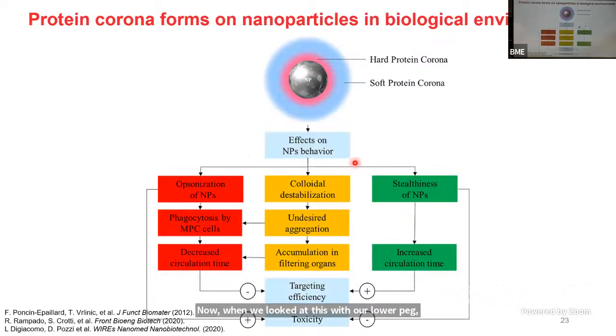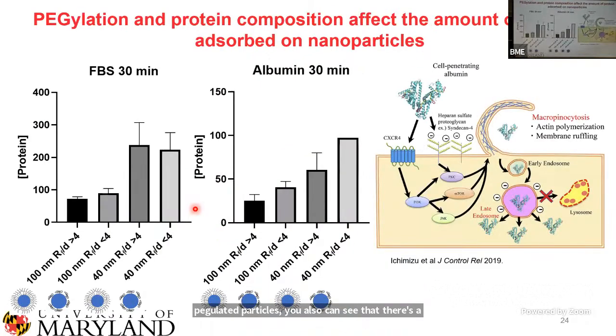For instance, it can affect colloidal stability, and it can affect the stealth properties, so whether or not the immune system can detect the particle. It can affect opsonization, so again, activation of the inflammatory response, which would cause phagocytosis and removal of the particle. So there are a lot of things that can be influenced by this protein corona. We initially set out to do some, more or less fresh off the lab data, where we're starting to look at what happens, in terms of both size and surface chemistry, to the proteins on the surface.